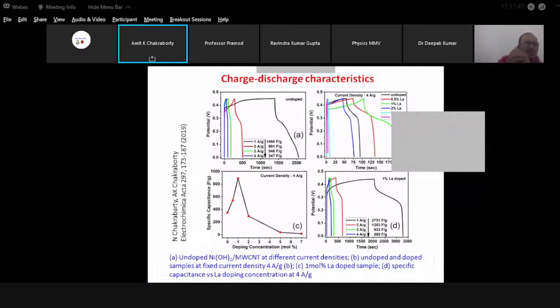So for testing of cycle stability, it is important to study the charge discharge characteristics, and here you have plotted the charge discharge characteristics as a function of different current densities. And of course, as shown by Professor Tan also, as you increase the current density, the values significantly reduce, and that's a common phenomenon, and there is a lot of research on how to improve this. However, at 4 ampere per gram current density for the undoped sample, this is so narrow. When we use the dopants at 1% lanthanum doping, we get the green curve, which is much larger than this curve here. So that means the dopant has made a significant contribution to the improvement of the property of the electrode.